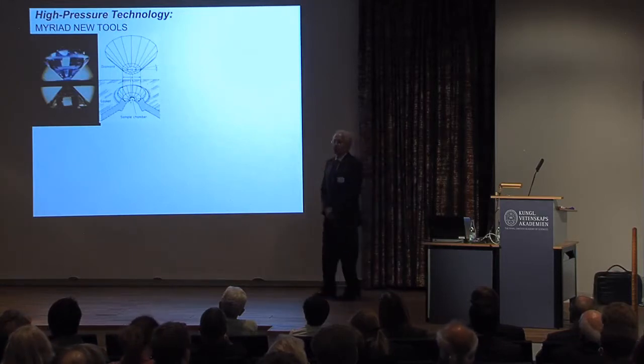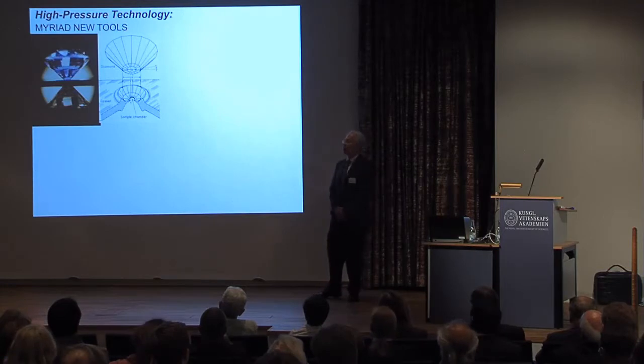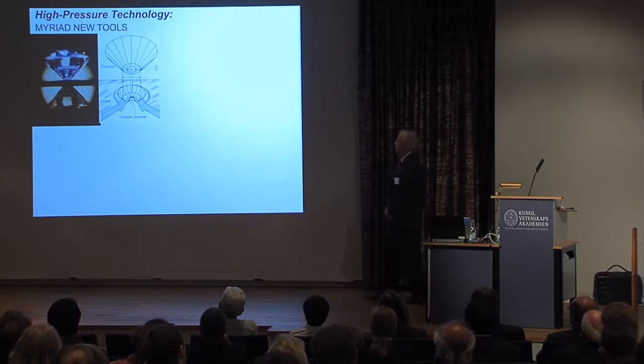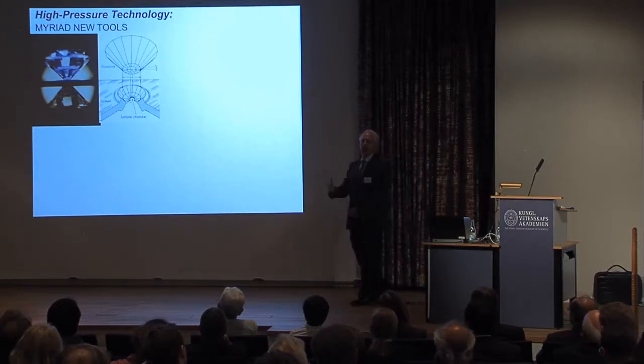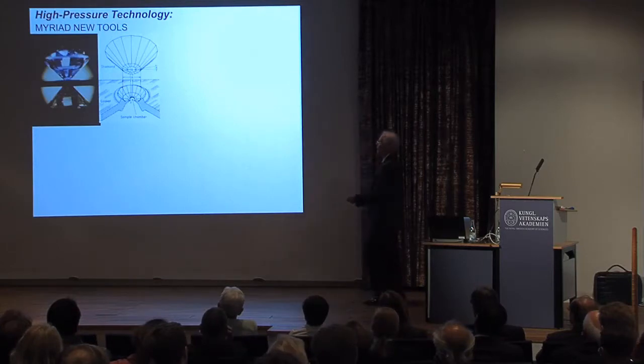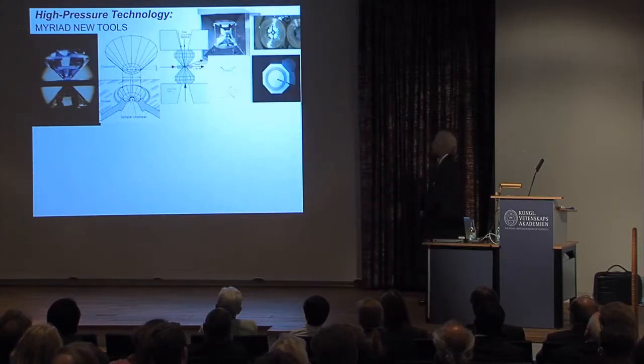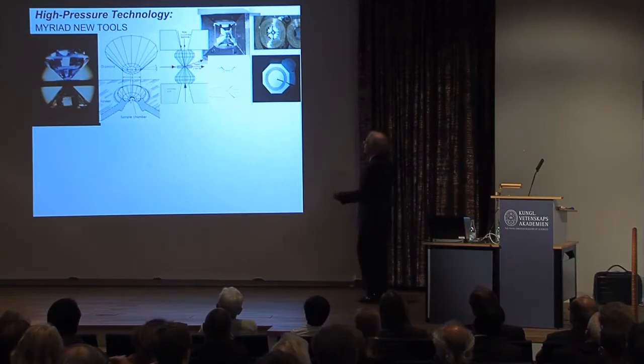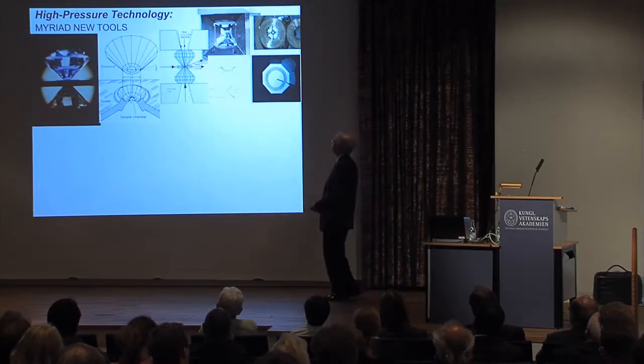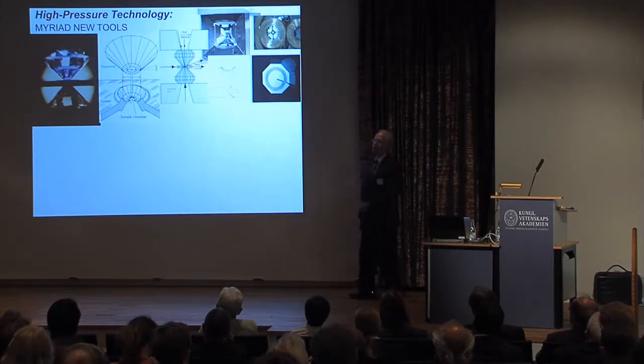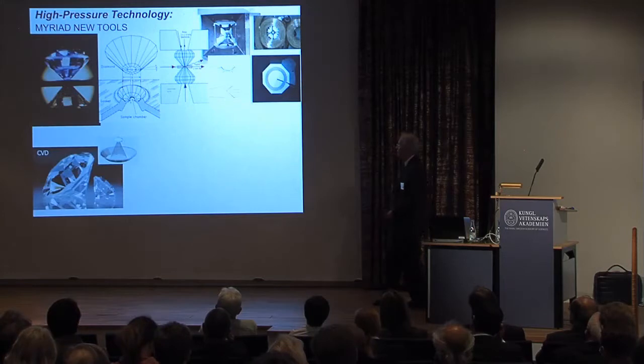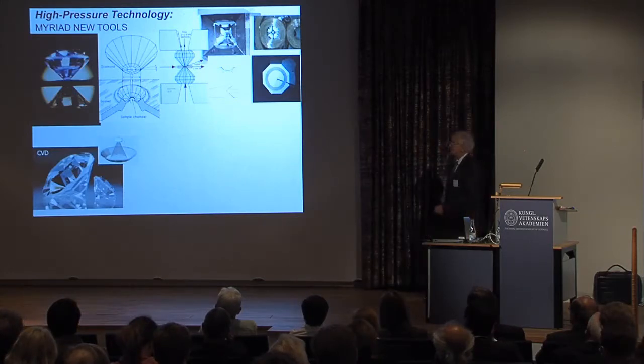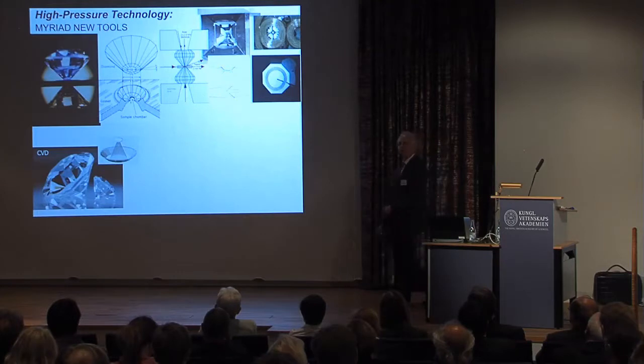And what's made it possible has been the development of a variety of tools based on instruments that use very strong materials for studying materials under sustained high pressures, and typically one uses diamond in some fashion because it is a very strong material and it's a window on the sample so you can watch materials transform, behave in situ at high pressures and temperatures. But really, a large number of different kinds of tools based on this simple design have been developed, allowing a variety of different kinds of measurements to be done, including measurements of transport properties, of magnetic properties, electrical properties.